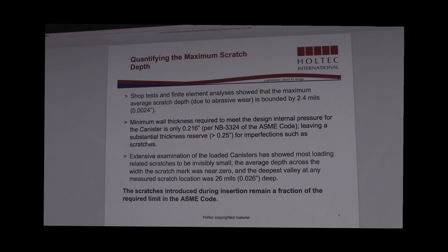Now, that number takes into consideration the minimum strength properties of the material as well as the applicable metal temperature. But for a canister of our size and dimension with 100 PSIG internal pressure, the minimum required thickness to meet NB-3324 is 0.216 inches. Keep in mind that the nominal wall thickness for our canisters is a minimum of a half inch, and there is an option as well that the thickness can be 5/8 of an inch thick. So there is a substantial thickness reserve, more than a quarter inch, that's available for imperfections such as scratches and other considerations as well.